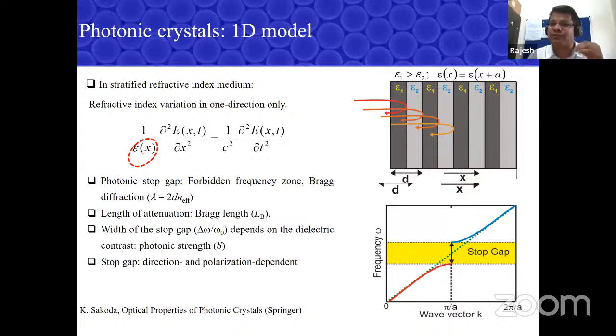That is what is called a frequency gap or a band gap for light in this direction of propagation. This band gap depends on angle because this is an interference process. The moment you change the angle, the condition changes, and it also depends on the polarization of the light. If you solve a dispersion relation for a periodic system like a semiconductor, and plot frequency versus wave vector, you get a gap in frequency at a wave vector pi by a. Why pi by a? That is the wave vector where you satisfy the Bragg condition for the light.